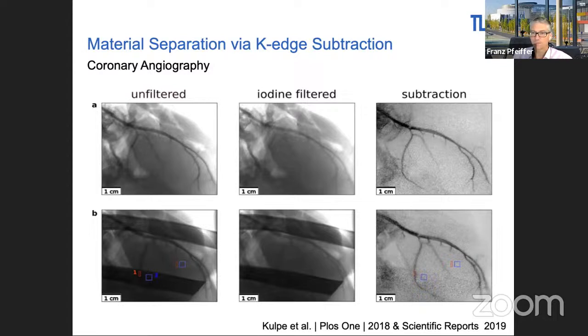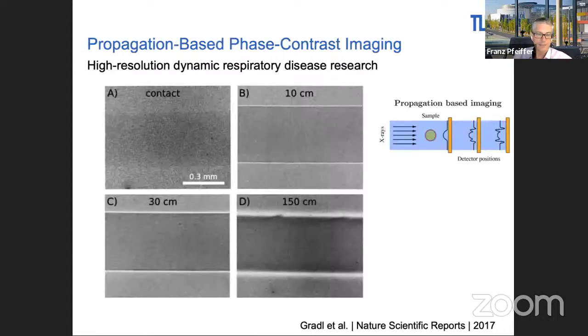Yeah, we can do very nice imaging and also do phase contrast imaging applications of various sorts because we have a rather small source, in both directions. Together with this homogeneous beam, we can nicely see, for example, propagation fringes. In the contact regime, you only get the attenuation, and then as you propagate further and further, these fringes expand and give you additional contrasting features.